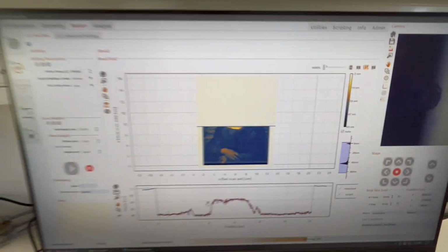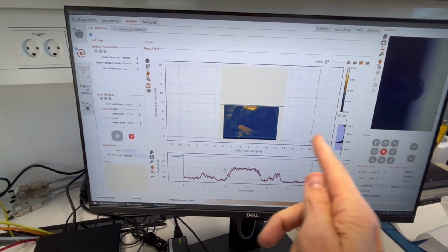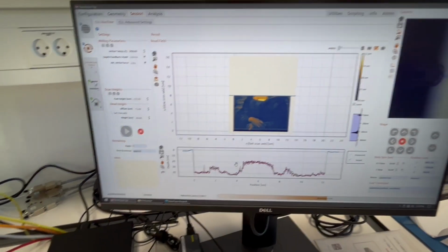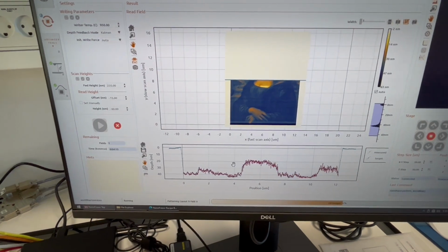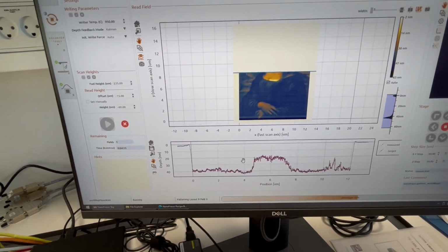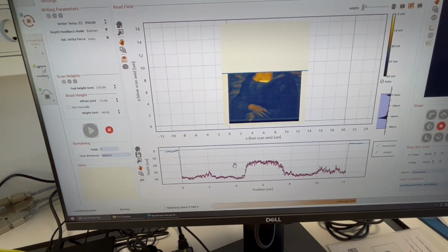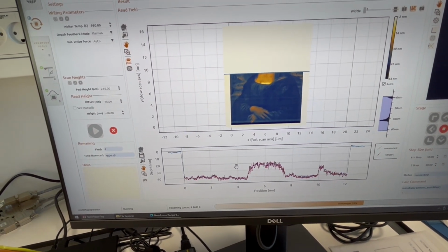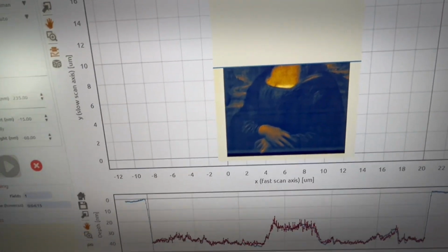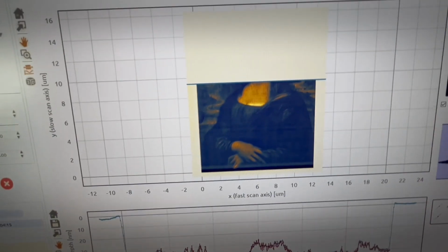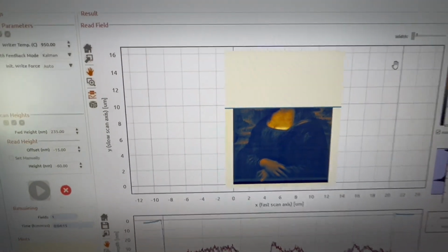Here, you see from the background that the tip is patterning in real time. It's very fast. And this pattern is made by the tip being heated up and cooled off super fast, and whenever it's hot, it's evaporating the polymer. It pushes the surface down, and then the polymer decomposes, sort of sublimates, and by controlling how hard you push down, you can control the topography of the surface. And you can see that the height is a range of about 50 nanometers.